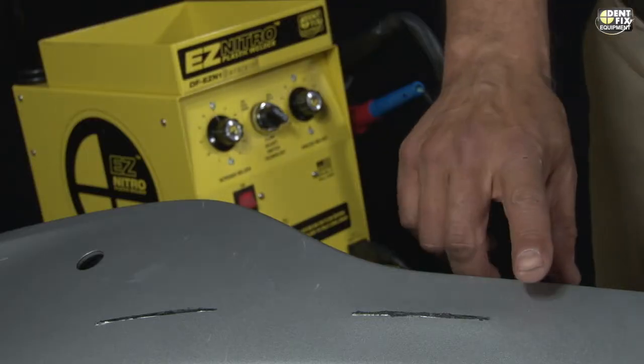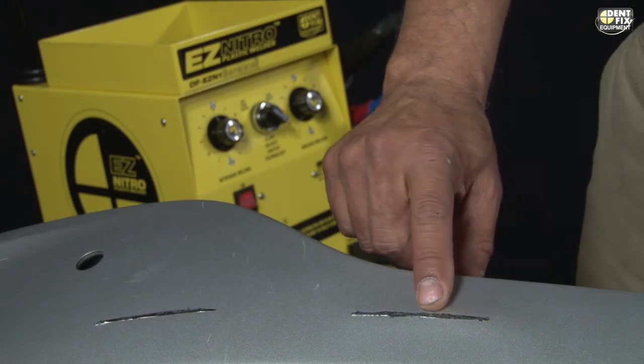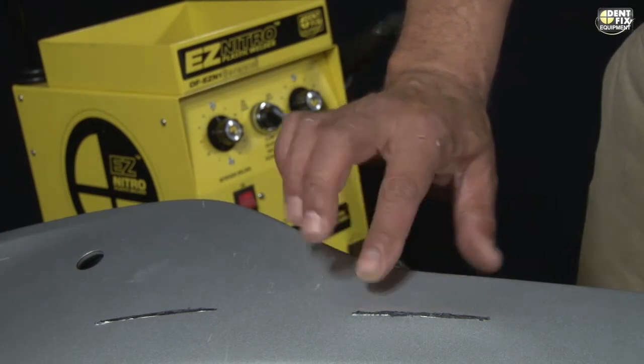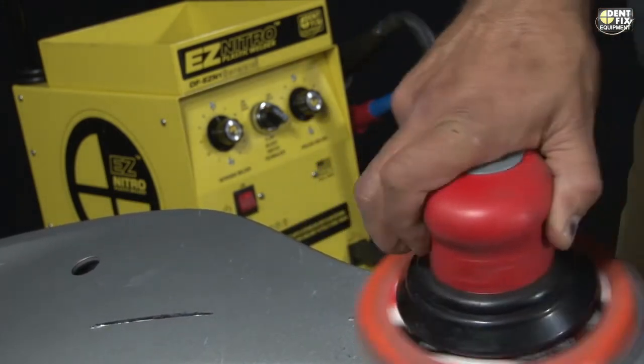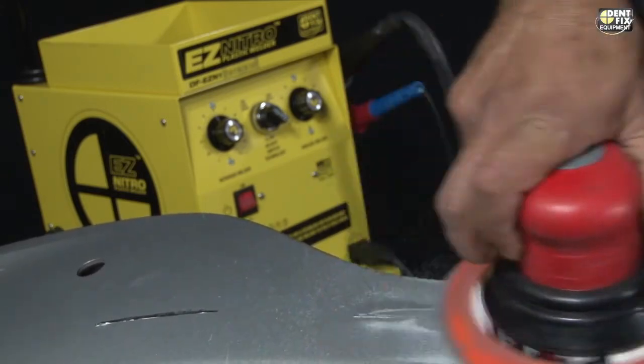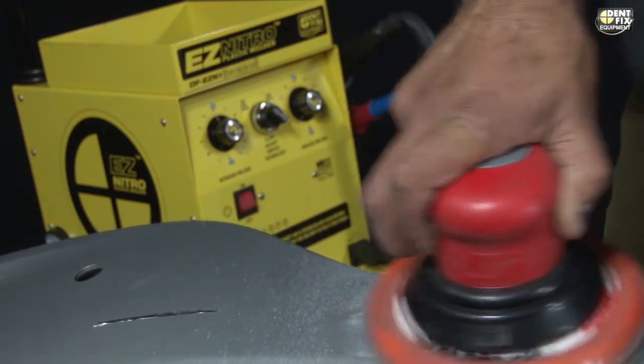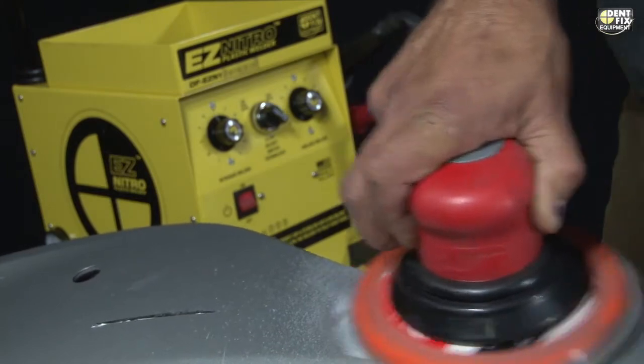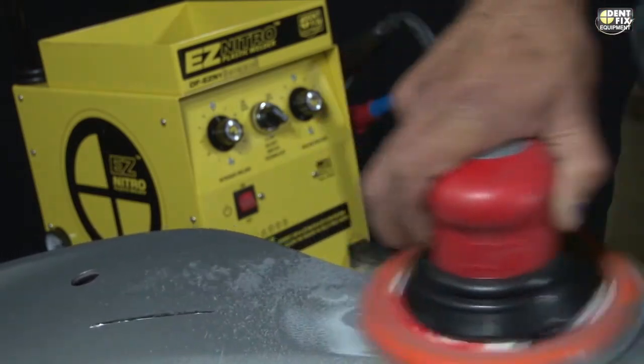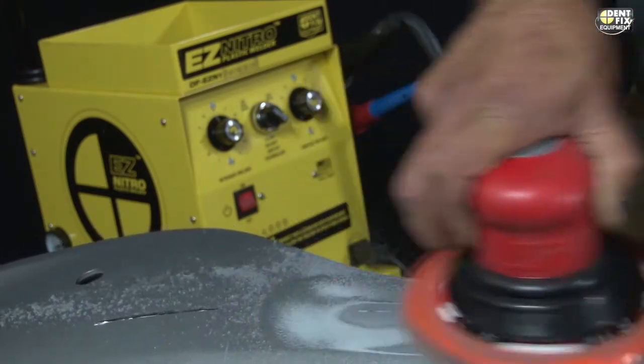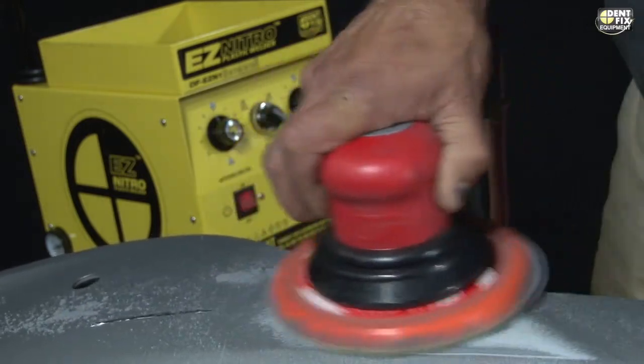We flip it over, remove the tape, and look at the front. You will see the penetration we got through with our backside weld bleeding out of the crack. And after sanding it with a dual action sander and 80 grit sandpaper, you can truly see the penetration we got through that weld. Many times a one-sided weld will give you complete penetration on your part.